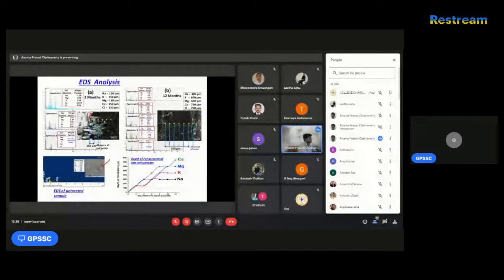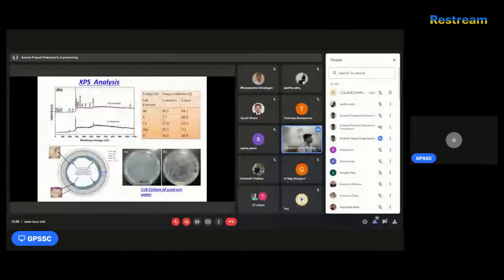Okay, so then we have gone for X-ray photoelectron spectroscopy, and we could realize, at 2 months and at 1 year, what the extent of atom percentage deposited is, and why. Sodium is deposited much more, while calcium is deposited nearly the same. So that means sodium is penetrating much more.